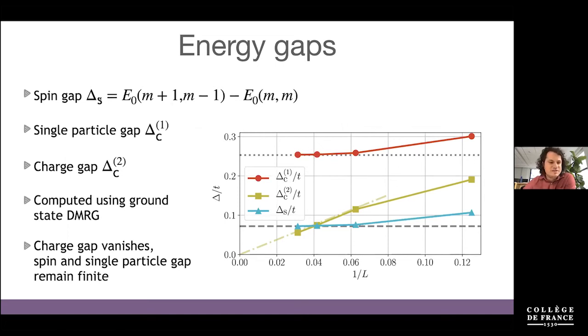And the way to do this is one can simply do this by computing ground state energies. So here I'm, for example, giving the formula for a spin gap, which is: compute the ground state energy of a system with m+1 and m-1 particles, and subtract from it the ground state energy of the system with m and m particles. And there are similar formulas for a single particle gap, which is if I add 1 electron, and the charge gap. This is computed by adding 2 electrons or removing 2 electrons. And this is different for the Hubbard model. As we've seen before, adding 1 electron has its own problems and has a bit different energetics than adding 2 electrons. So that's the differentiation between a single particle gap and charge gap.